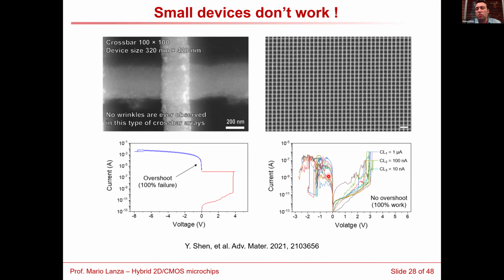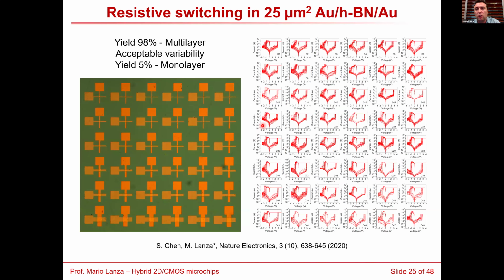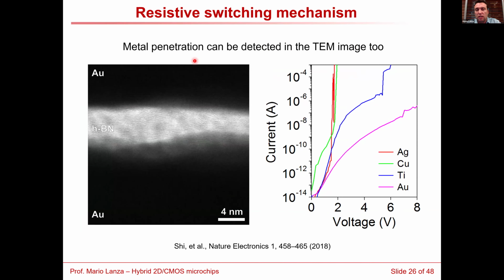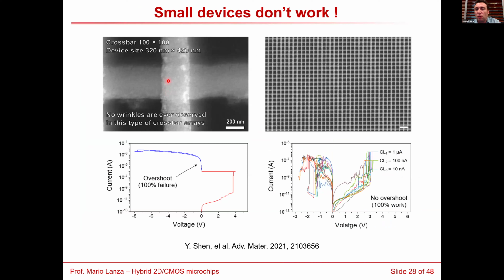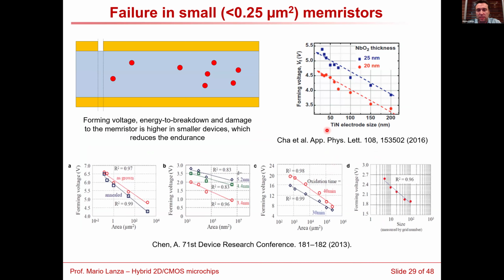So basically the conclusion is that for our 25 micrometer square devices, as you see here, all the devices work well. But for the small devices, most of the devices fail in the first cycle, and the ones that don't fail in the first cycle fail very quickly in the next cycle. So nothing works, basically. And then we were very upset, but let's understand why this happened.